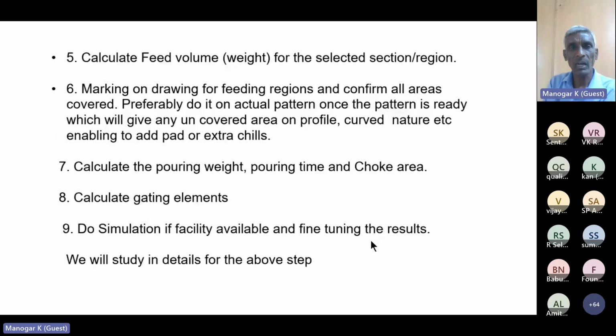Calculate the feed volume or the weight of the selected section, marking on the drawing the feeding regions and confirming all the areas are covered in case of bigger castings. Preferably do it on the actual pattern. Once the pattern is ready, when it is convenient, if any uncovered area is there, you can plan for a chill, extending a pad or additional risers. Calculate the pouring weight, pouring time and choke area. Calculate the gating elements. Do simulation if facility is available and fine tune the results.